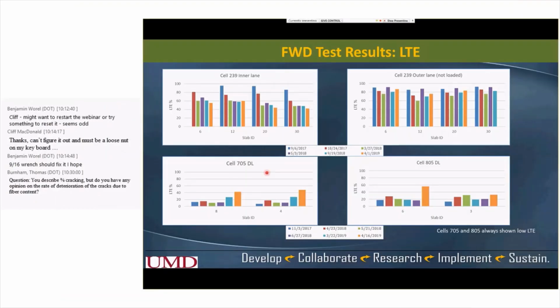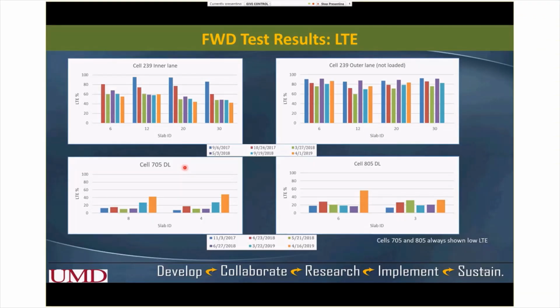Now cells 705 and 805. You may be surprised looking at this data: the load transfer efficiency is very low since the beginning. Now, what is load transfer efficiency? Load transfer efficiency is the deflection under the unloaded slab divided by the deflection under the loaded slab, multiplied by 100, and we get the result in percentage. Load transfer efficiency has been low for both cells. Keep this in mind, and then we will see what kind of faulting we have seen in these two cells.